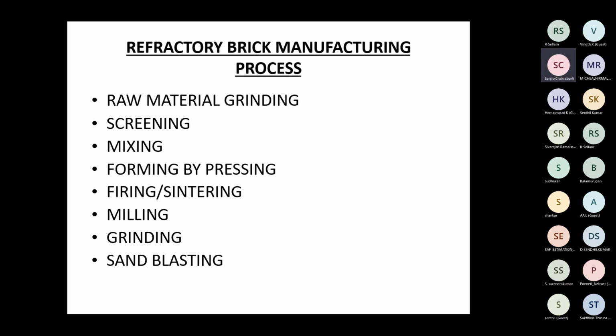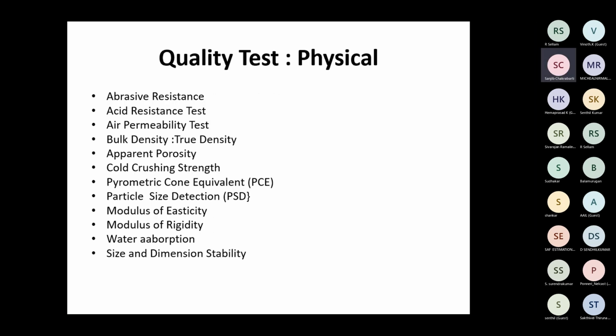In milling, after firing and cooling down, they mill the surface because of the dimensional tolerance. Everything has a dimensional tolerance as per ASTM, the American Society for Testing and Materials. So you have to follow the guidelines of this ASTM. Milling means the surface has to be milled, machined.